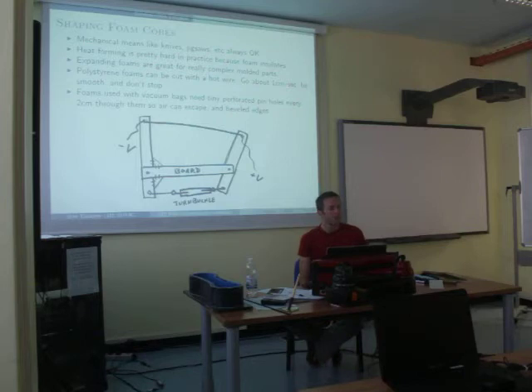Heat forming with foam is pretty hard actually, because the foam is a good insulator, so you need to have the whole atmosphere that you're doing your heat forming in heated to the right temperature. You can use an oven for this if you want, or maybe a small toaster microwave thing might work too if it's a really small part. But it's pretty hard to do. I was disappointed. I tried several times to heat form and I'm not very good at it. I don't have the right tools. Expanding foams are what I used for the really complicated parts.